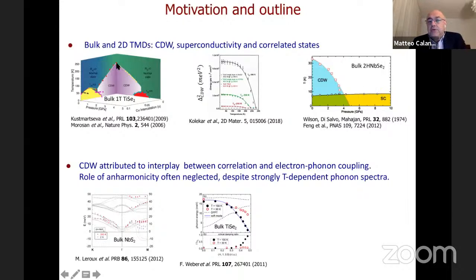On the contrary, here the situation is different because at the emergence, when the charge density wave emerges, superconductivity has some kind of dome feature. Actually, these two facts can be traced to completely different behavior of the phonons. In the case on the right, the charge density wave is determined by the low energy phonons, but superconductivity is phonon mediated and is due to high energy phonons. The high energy phonons don't feel too much the charge density wave instability, and superconductivity has an almost constant critical temperature, slightly increasing with pressure.